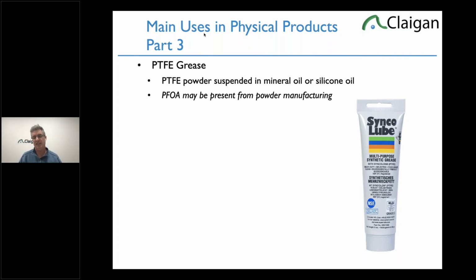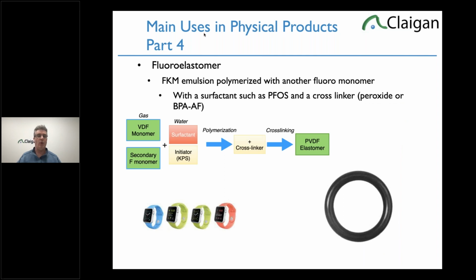The powder, instead of being fused, is suspended in mineral oil or silicone oil. It can have PFOA present because PFOA can be used to control the powder side of PTFE by being a surfactant in the manufacturing process. It's unintentional. You wouldn't have to declare it. You would just declare the PTFE powder. However, you still have to be PFOA free for the purposes of Europe. So that's a typical lube. Where a lot of the industrial products use fluoroelastomers like FKM.